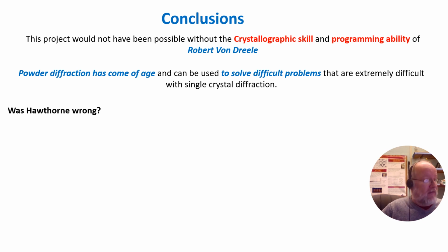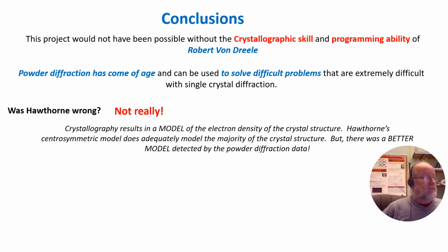has difficulties with. So was Hawthorne wrong? Well, not really. With the data he collected, his single crystal data, there was very little indication that there was merohedral twinning. So solving it in a centrosymmetric crystal structure, well, almost everybody would have done that. And it adequately modeled the majority of the crystal structure. We had the advantage with our powder diffraction data because powder diffraction doesn't really see twinning very well. Therefore, it led directly to the non-centrosymmetric model.